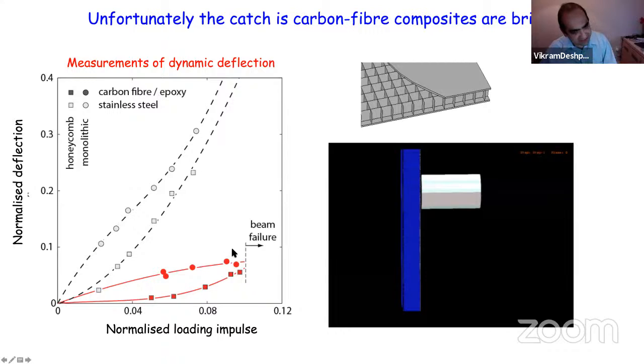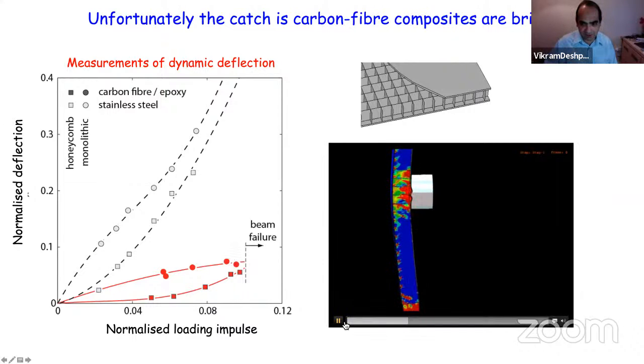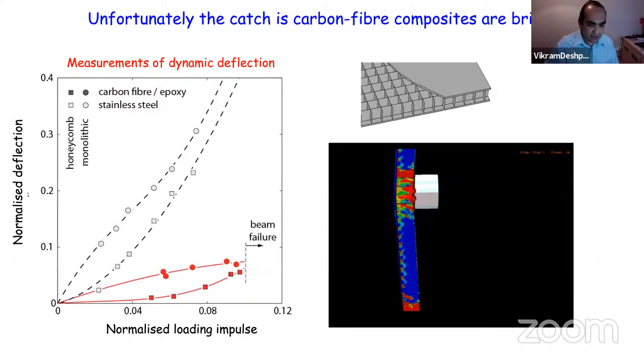But the catch is that carbon fibers are brittle. And because they're brittle, they fail here. While the metals will not fail, they will just continue to go up, to much higher impulses and deflections. They're ductile. The carbon fibers fail. For example, this is a simulation where you can see that the carbon fibers have completely failed. They have a 1 or 2% failure strength. And nobody is going to use a structure which says, I'll do better if somebody hits me slowly, but I will completely collapse if I get hit hard. Nobody will actually use such a structure.